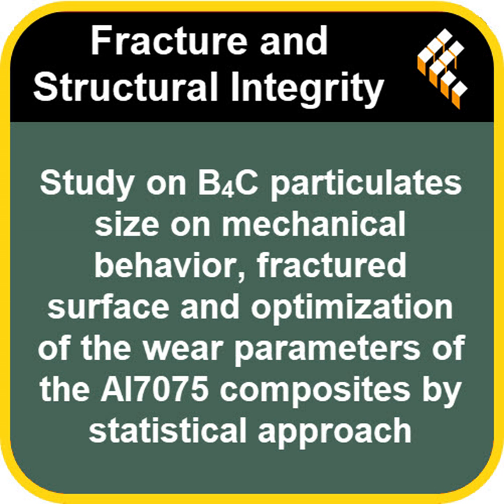Again, kind of backwards. You'd think more sliding equals more wear. You would. But the thinking here is that a couple of things happen over longer distances. First, a protective oxide layer can form on the pin surface, acting like a shield. Second, the wear debris generated, the tiny bits that break off, can actually get compacted into the valleys of the surface texture. So they fill in the gaps. Yeah, they effectively smooth out the surface at a microscopic level, reducing further abrasive action.